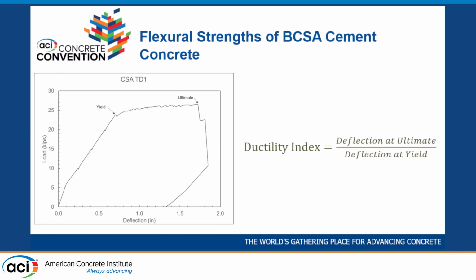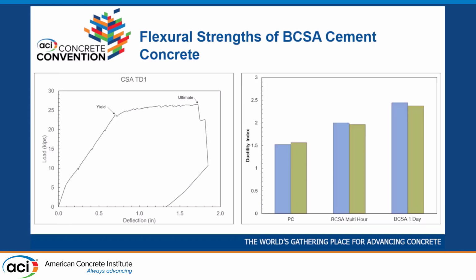So another kind of cool thing we found, we looked at this thing called the ductility index, which is if we take the deflection at ultimate load over here and divide it by the deflection at yield, we get kind of a scalar value that tells us how ductile the beam was. And we found that the BCSA beams were more ductile than the Portland cement beams. And this improved over time, so they became more ductile after 1 day. And it's kind of interesting because these ones were actually weaker concrete than the Portland cement beams. So in spite of it being weaker concrete, we had more ductility. And the only way we could really think to explain this is maybe it had something to do with the ultimate compression strain in the BCSA cement being different from the Portland cement concrete. So this led us to want to investigate this further.